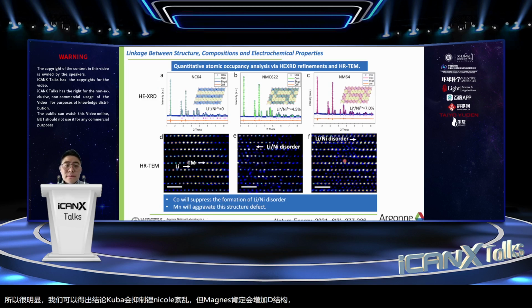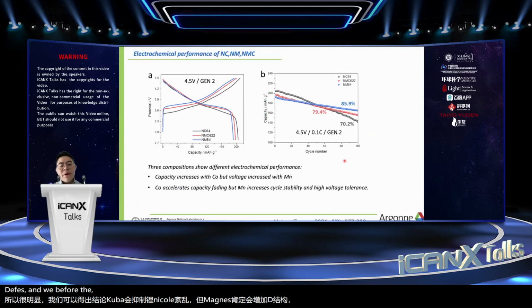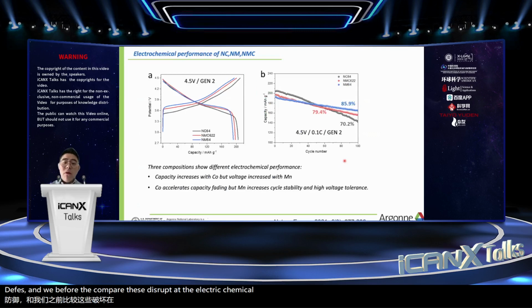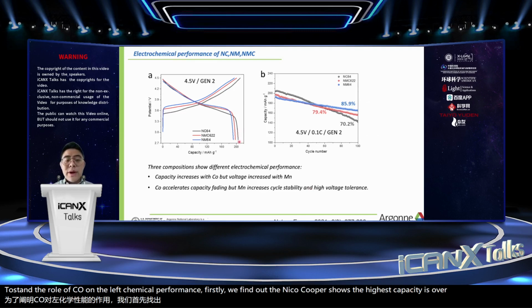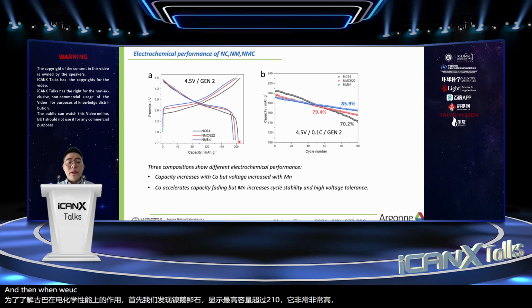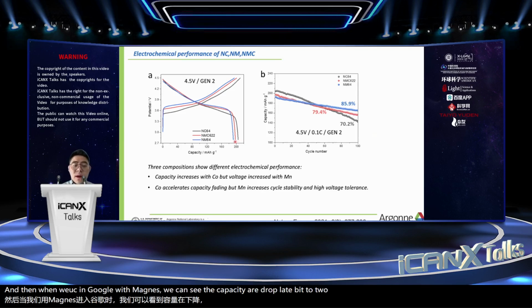And we further compare the electrochemical performance of these 3 materials to understand the role of cobalt on the electrochemical performance. Firstly, we found out the nickel cobalt shows the highest capacity, over 210, which is really, really high. And then when we reduce cobalt with manganese, we can see the capacity drop a little bit to 200. And then when we completely remove cobalt, we will have only 190.